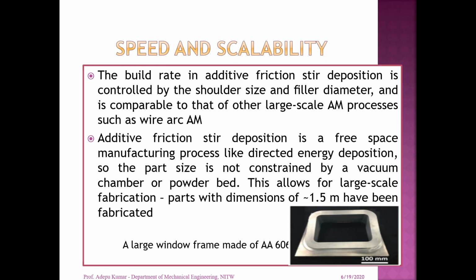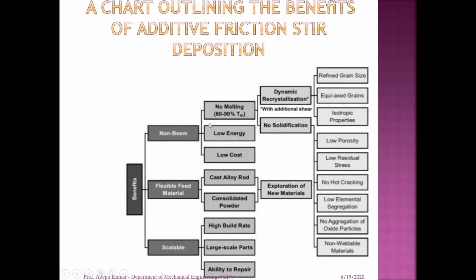Then what are the benefits with respect to the different categories? One is non-beam, flexible feed material, and scalable. Because of being non-beam, there is no melting, low energy, and low cost. Using dynamic recrystallization and no solidification, you get a refined, equiaxed grain size and isotropic properties. Then flexible feed material, either cast or consolidated powder; you can make powder metallurgy components. Then exploration of new materials; you can add different materials. No hot cracking, low elemental segregation, no aggregation of oxide particles, and even non-weldable materials can be processed. And a scalable, high build rate, large-scale parts, and the ability to repair. You can also repair structures.